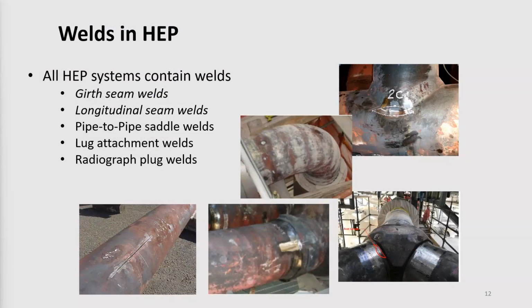All of these systems contain welds. So I drew attention to these failures in the long seam welds, and thankfully we've learned enough that there are not many long seam welded components in the combined cycle plants. I'm aware of only a few clamshell welded elbows and things like that. But these same issues occur in other welds in the piping systems, most notably in the girth seam welds. But then you have pipe-to-pipe saddle welds, lug attachment welds, radiograph plug welds, all of which can be locations of problems as the piping systems age.